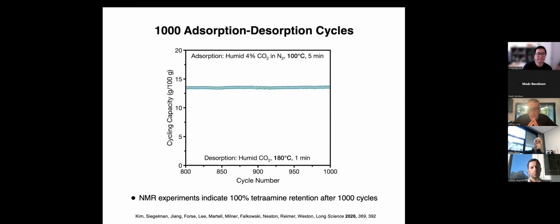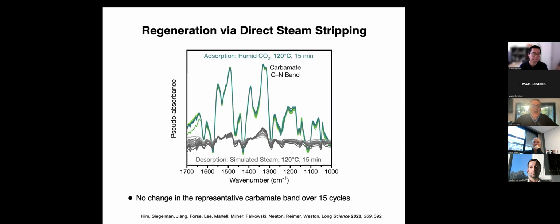When we saw that these could operate under extreme conditions, we thought perhaps we could regenerate with steam, do direct steam stripping of the CO2. And so those are very harsh conditions for most adsorbents. They're not going to tolerate it. But these are very stable. These tetraamine appended materials are very stable. And in fact, you can regenerate using direct steam stripping. And this is showing just isothermal CO2 adsorption and desorption. These are infrared spectra, and the central band is the carbamate CN stretch, and showing that this chain forming mechanism is operational.